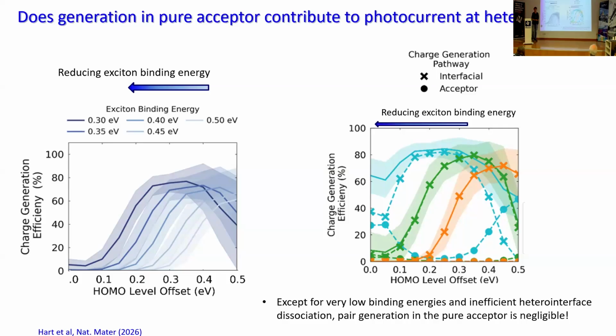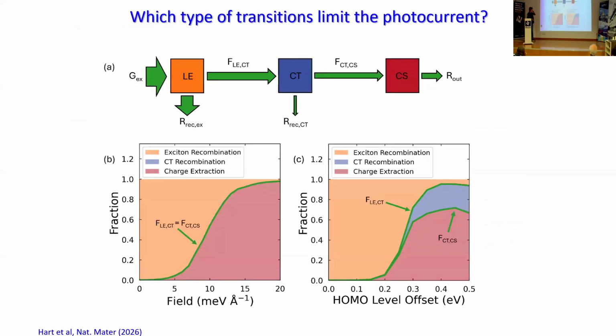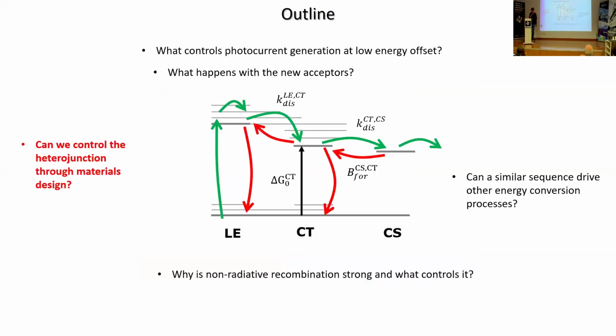Most photocurrent comes from exciton dissociation at the interface, except if you go to conditions where the exciton binding energy is very small, and then it's easier for the exciton to break up in the acceptor domain itself and generate some significant photocurrent there. But if that were the case, other behavior would be different. So we think that's out of the regime of properties of materials that we have at the moment. So then you can see what, I'll skip that. So I think I'll make this the last topic here.